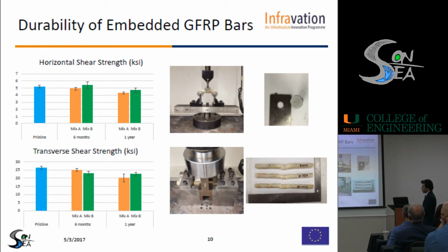After a year, well, you have to know that under accelerated conditioning, the property of the bar is supposed to go down, because that is a really, really harsh environment. You have it inside the concrete, and that's almost a boiling kind of seawater. So you have chloride, all kinds of chemicals in the seawater, and also the temperature. So those are all affecting. So going down is not a bad thing. We are expecting that this goes down, but it's really amazing that for seawater concrete, we actually got higher results in horizontal shear and in transverse shear after a year. So it seems that seawater concrete actually helps the durability of your GFRP bar.